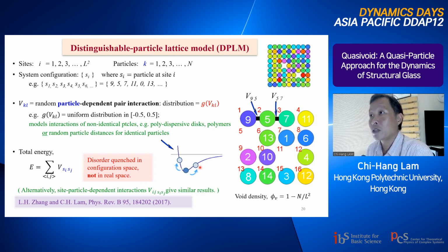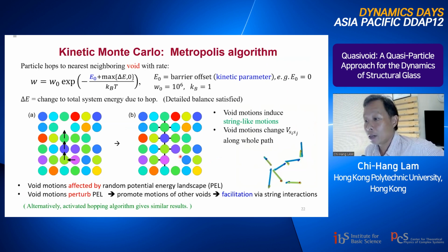So the average distance between any two particles in a frustrated system is not at the well. So there is energy disorder due to positional disorder. I think there has been a lot of belief that positional disorder is not important, except that it gives rise to the energy disorder. So in most studies of the lattice models, in our approach or other approaches, we implement the energy disorder without the positional disorder and try to reproduce glassy results. And then hopefully the result justifies the assumptions.